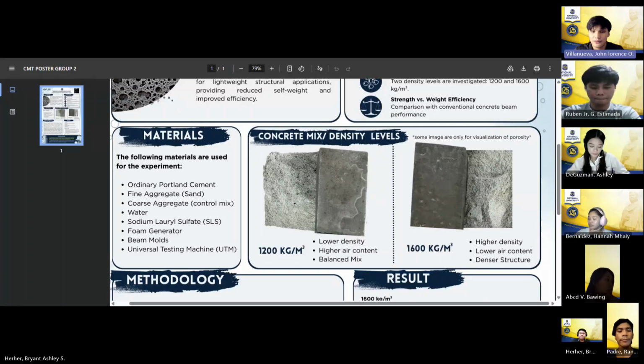7.84 megapascal. Conversely, the 1,600 kilogram per cubic meter mix represents our higher density level. It features a lower air content and a much denser structure. This balanced mix yielded a superior, more stable flexural performance ranging from 7.4 to 8.1 megapascal, along with significantly improved crack resistance. Ultimately, choosing between these configurations is a direct trade-off between maximizing weight reduction and maintaining structural reliability. For the methodology, Mr. Padre will discuss.